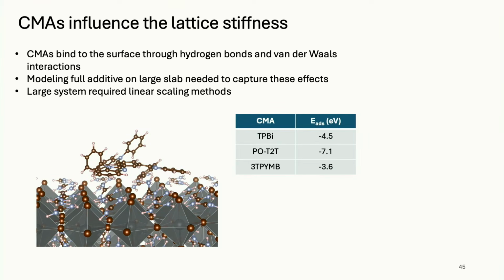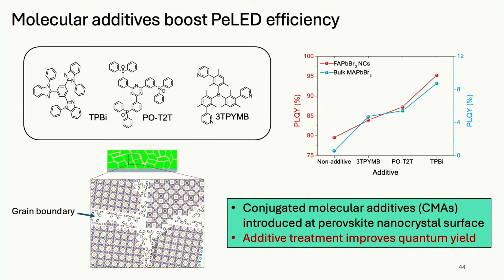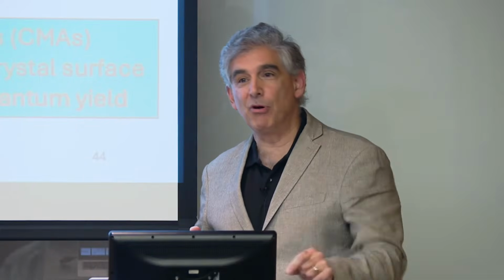So here is our idea. How do we think about these molecules? They have multiple attachment points. That's what I really should have showed you. Here, remember we think that an amine can be a group that kind of hydrogen bonds to the perovskite surface. This has 6 different N groups. This one has 3 phosphonium groups, and this one has 3 nitrogens as well. So they're connecting to the surface in multiple places, okay? So my analogy is, if you suddenly have a small earthquake tremor, what do you do? You try to grab different points on your desk to stabilize things so nothing falls off, you see? And so no one ligand attachment point will stabilize anything.